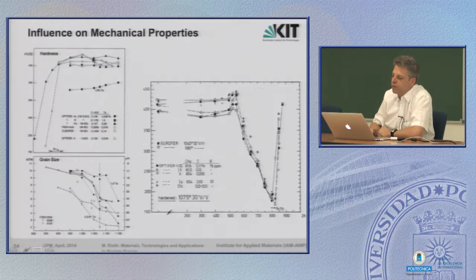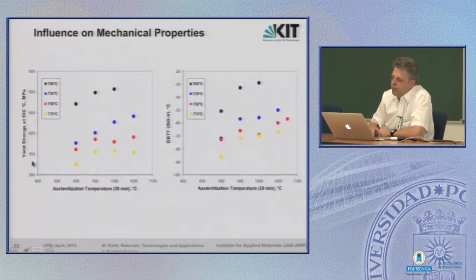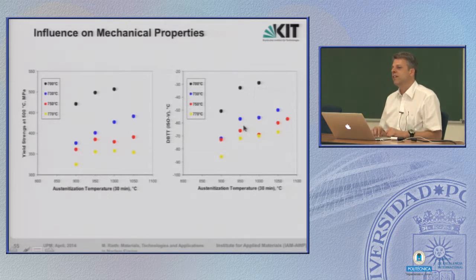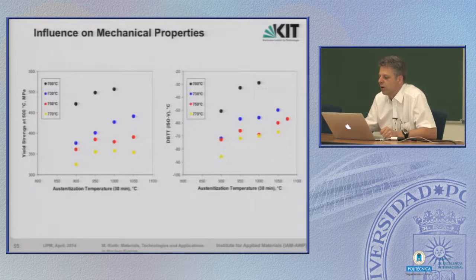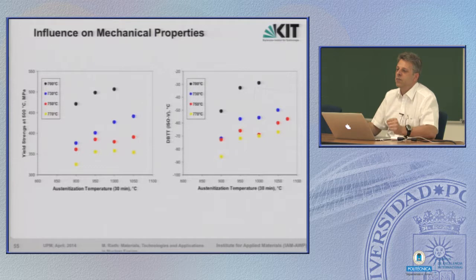So here, this is the effect of annealing. This is the effect of tempering. And finally, here is an overview, a plot of yield strength, a plot of DBTT, depending on the austenitization temperature and tempering temperature. And what you can see, without going into details, is that you can tailor-make your Eurofer material. Depending on any combination of heat treatment, you can produce very different material behavior, tensile strength or brittleness, DBTT shift, whatever. And this you cannot do, again, with austenitic steels. That's a very specific feature for martensitic steels. You can vary the material properties in a broad range merely by heat treatment.